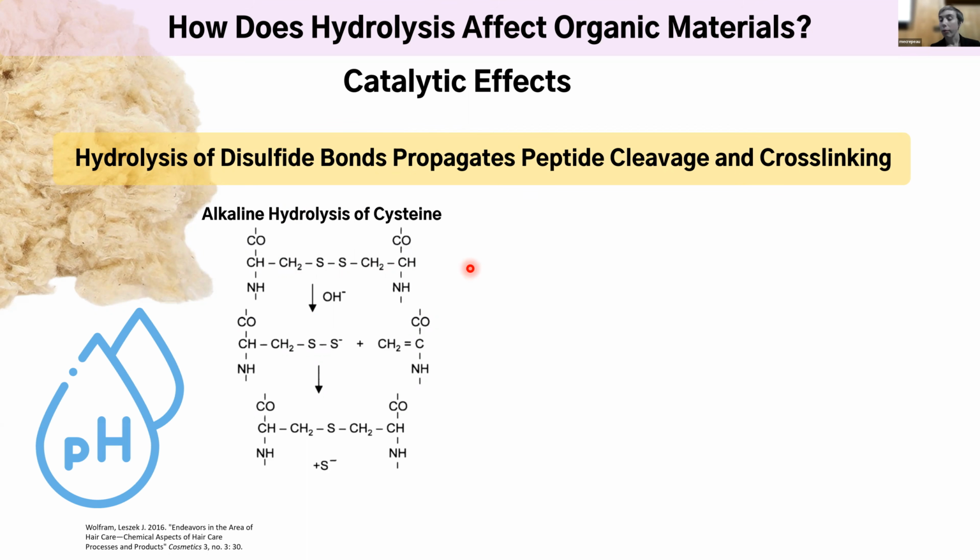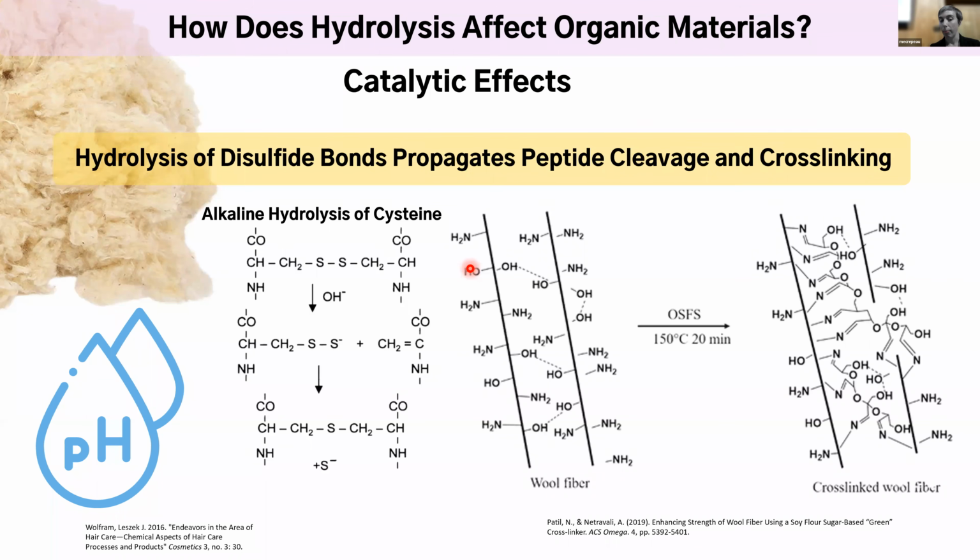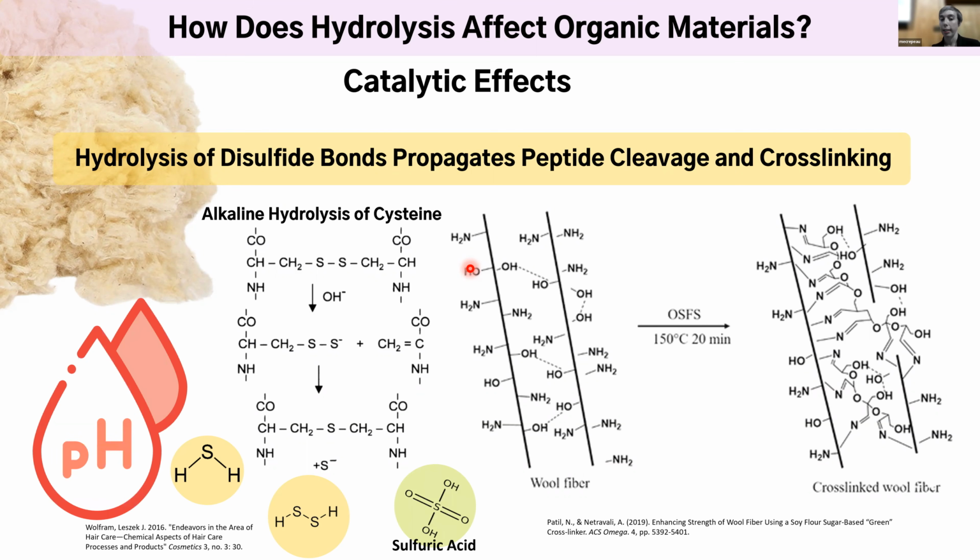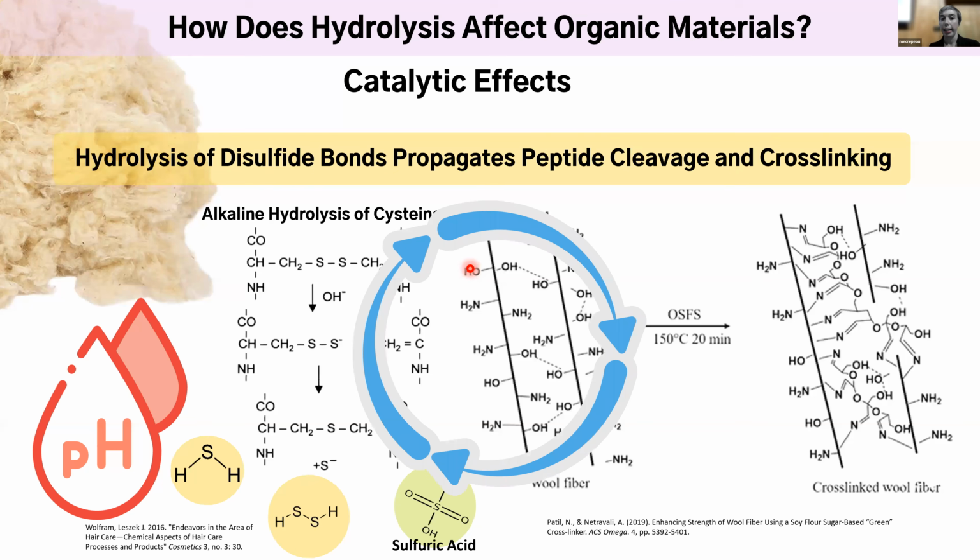And then when you add moisture, for example, and all of a sudden an acid, you do get recombination effects, with these cross-linked chains starting to break apart and then recombining in different ways. But you also have that sulfur that's part of that cysteine bond being ripped out of the structure and left to its own devices. And so it will start to combine with other things and form other materials, including sulfuric acid, in which case you get this self-perpetuating cycle of acid attack that is then perpetuating more acid attack within itself.